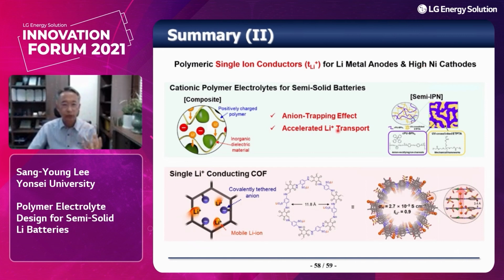This was based on the anion trapping effect, and due to the formation of nanoscale channels, we obtained accelerated lithium-ion transport. Finally, as an alternative to the inorganic sulfide-based one, we have suggested a COF-based solid-state electrolyte.